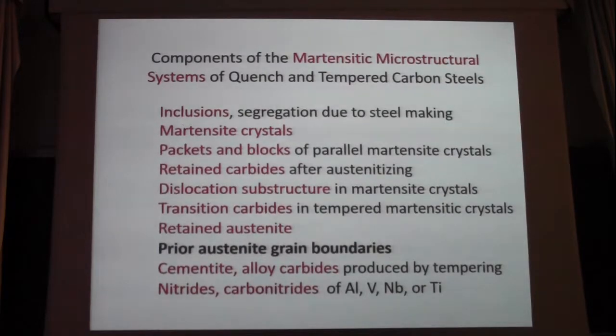Then there's retained austenite. Not all of the austenite that is produced at the high temperatures is eliminated by martensite formation. And the higher the carbon content of the steel, the more of the high temperature phase is retained in these martensitic microstructures. And then I've outlined here the prior austenite grain boundaries. This is where intergranular fracture occurs. What happened during austenitizing is carried over and becomes a very sensitive microstructural element in a quench and temper structure, and is related to these intergranular structures. Intergranular, what does it mean? It means between the grains, between the crystals.